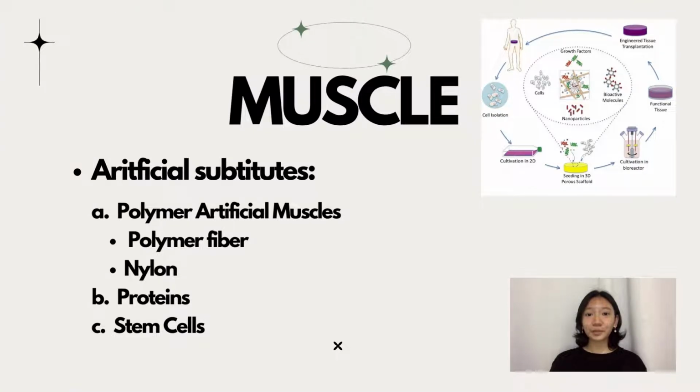Now on to the second polymer material used to create artificial muscles, nylon. Nylon was carefully shaped and modified and then selectively heated on one side to create a bending motion similar to that of a muscle. Researchers have demonstrated that the material can maintain its performance after at least 100,000 bending cycles and can bend and retract at the speed of at least 17 cycles per second. This nylon system could be used for self-adjusting catheters and other biomedical devices.